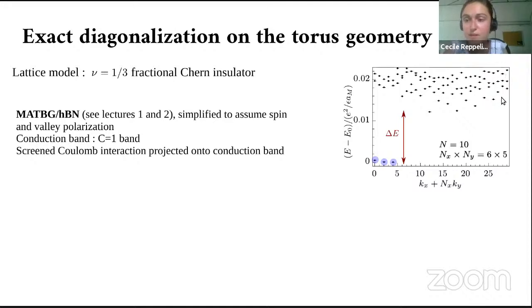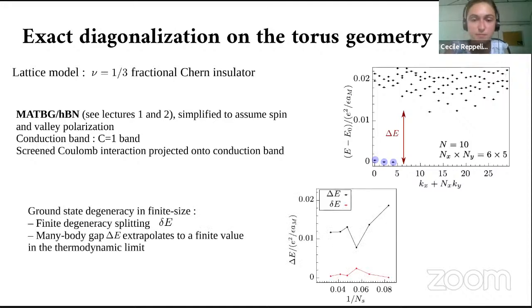Something very important with any numerical method, any finite size calculation, is I cannot trust what I get from just one size. I need to do the calculation several times for several different system sizes and compare the results. So here I consistently get this 3-fold quasi-degeneracy with a gap that's okay, though it depends a little bit on size, but seems to remain finite as I go toward the thermodynamic limit.